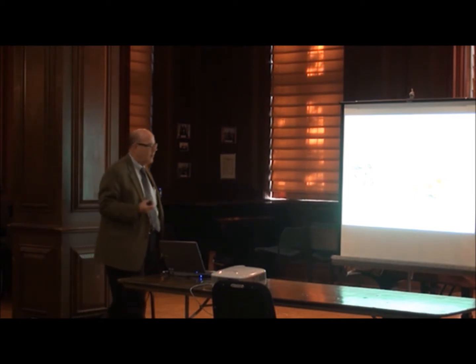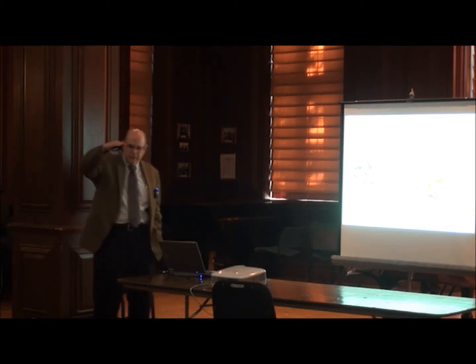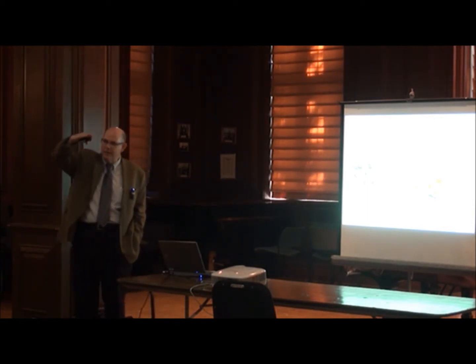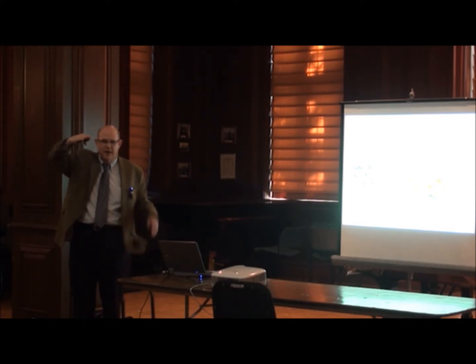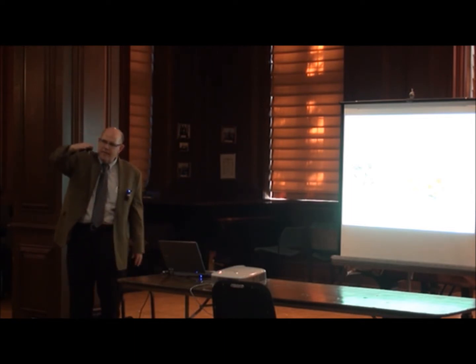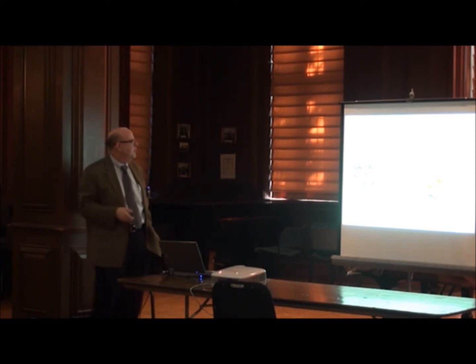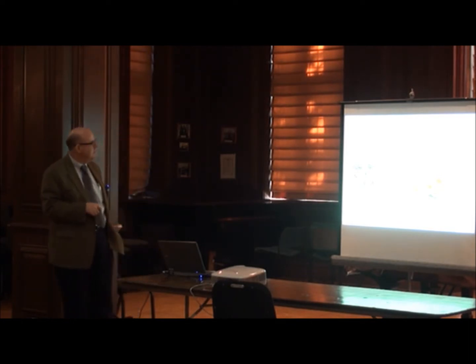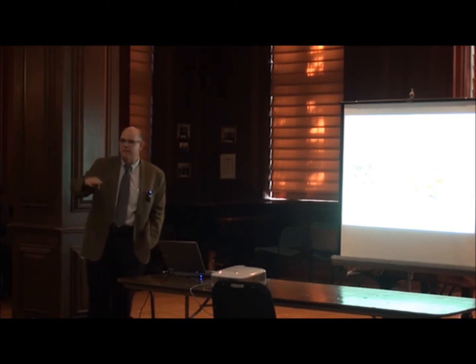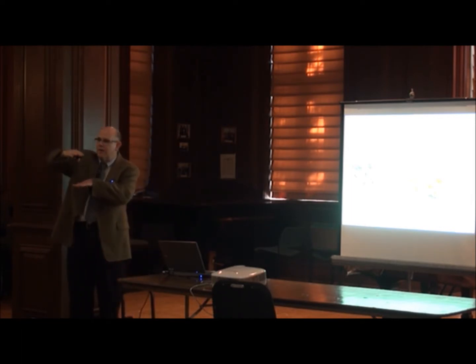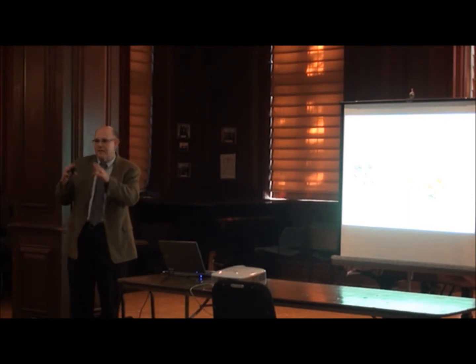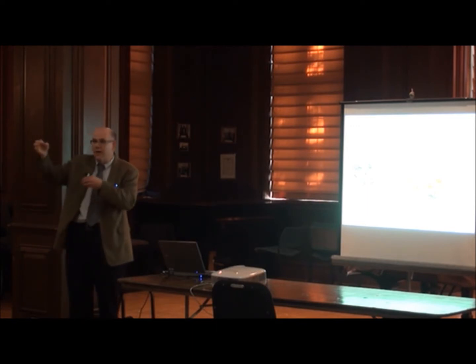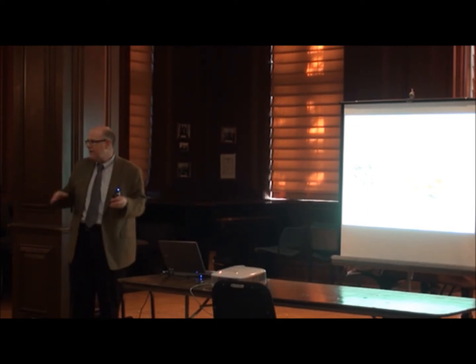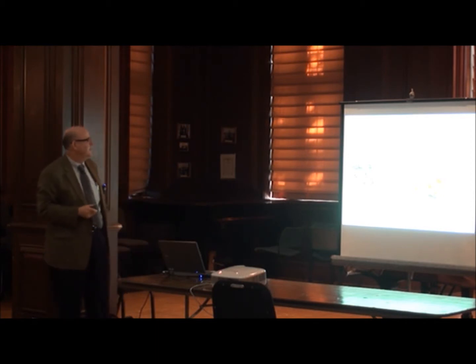But here's the interesting thing to visualize. Let's assume I have a perfectly flat plane coming down and it's perfectly mathematically smooth, and I'm touching a bunch of spheres. As I bring that plane down and I start hitting those spheres, what actually happens is that the mean asperity real contact area is actually independent of the force. In other words, as I push down harder and harder, all I do is find more and more asperities on which I'm going to sit. But the average size, some will be small, some will be large, but their average size will tend to be independent of the force, which is kind of neat.